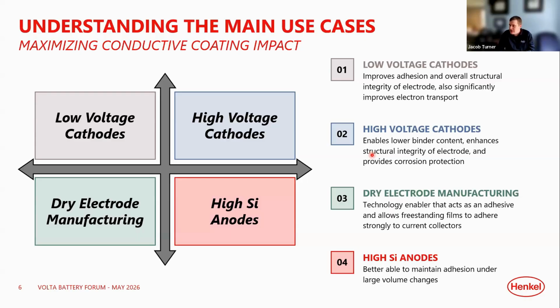Thirdly, the dry electrode manufacturing. So this is now, instead of looking at the active material case, taking a step back to how electrodes are manufactured. With dry electrode manufacturing, not sure the level of familiarity of everybody on the call, this is getting rid of NMP solvents, more of a lamination of freestanding films. And here, as we'll go through as well, a conductive coating changes from purely a coating to actually acting as an adhesive that allows for the lamination of these freestanding films to current collectors. Really enables this technology.